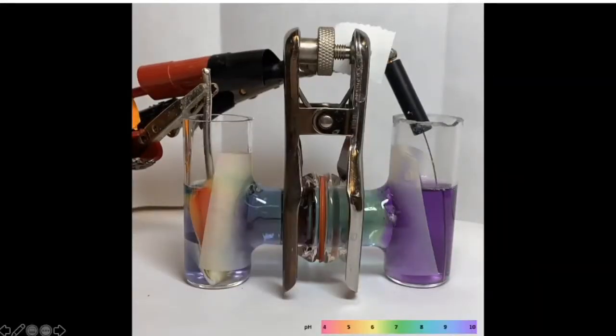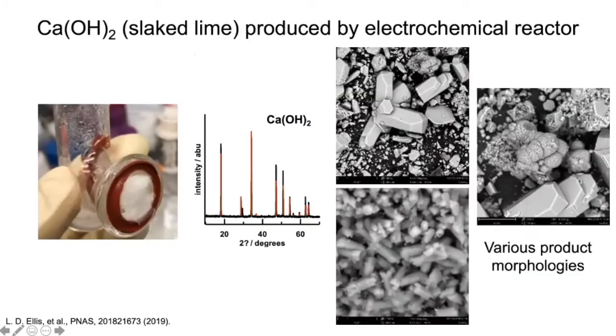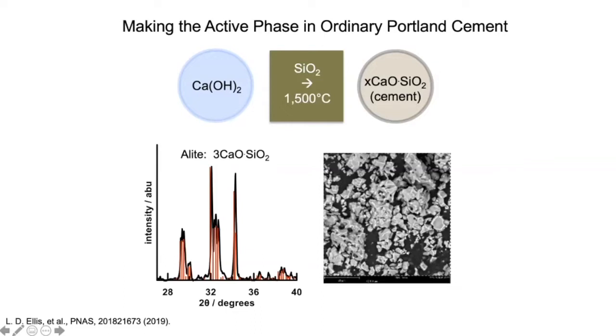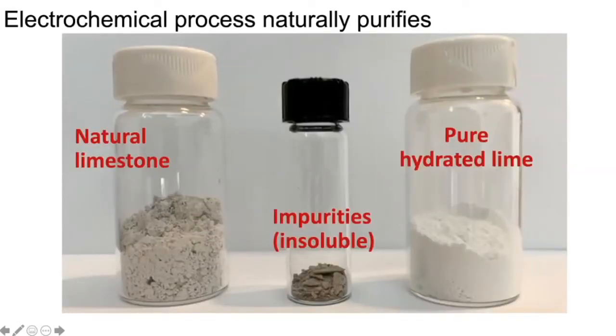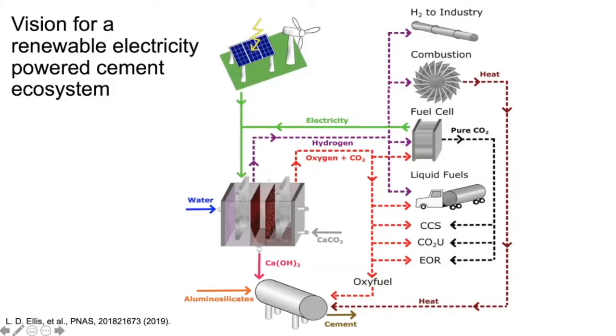I'm going to flash forward here. And I'll just show you what the calcium hydroxide looks like here. This is an electrochemical reactor for making calcium hydroxide. This is cement, the active phase of cement called alite, made with that calcium hydroxide. And this is what it does. On the left is natural limestone. When we send it through a reactor of this kind, first of all, it's selective. It purifies, giving us pure hydrated lime or calcium hydroxide in this case, and the precipitates are insoluble. Okay? And so what this leads us to is a scenario where renewable electricity could be used in an electrolytic setting, producing hydrogen if it's a water electrolyzer, not only for energy storage, but for chemical storage, which we can then use in a number of reactions.